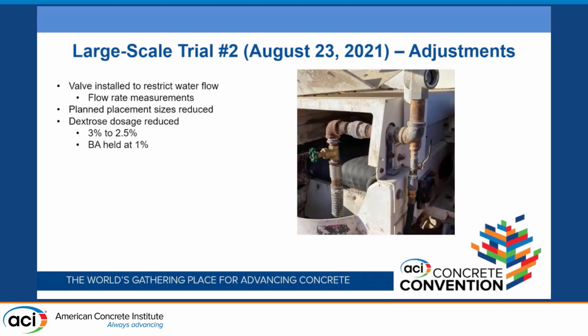So what we did to correct this is we installed a valve on the simplified volumetric mixer. That's just a valve right there. We went out there with a 5-gallon bucket and measured flow rates and figured out how many turns of this valve we needed to get our water cement ratio right. And obviously that comes along with the gate setting as well. So we measured the flow rate of the dry material coming off the mixer. Planned placement size reduced, and then we also reduced the dosage of dextrose from 3% to 2.5%, and we held the boric acid content at 1%.